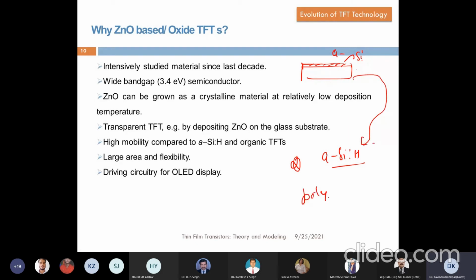Slowly they started with the polysilicon TFT. You might have heard about these displays. Still nowadays we call it LTPS. LTPS stands for low temperature polysilicon. For some few generations, Apple used LTPS TFTs, where you deposit the polysilicon with a low thermal budget on a flexible substrate or a glass sheet, and then you make the thin film transistors. These were the TFTs already available, but when you have a ZnO TFT, the fundamental advantage you get from the material is the transparency. Silicon band gap is always 1.12 electron volt. It is not transparent in the visible spectrum.